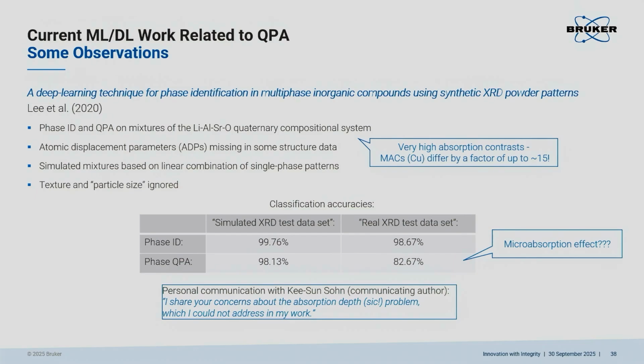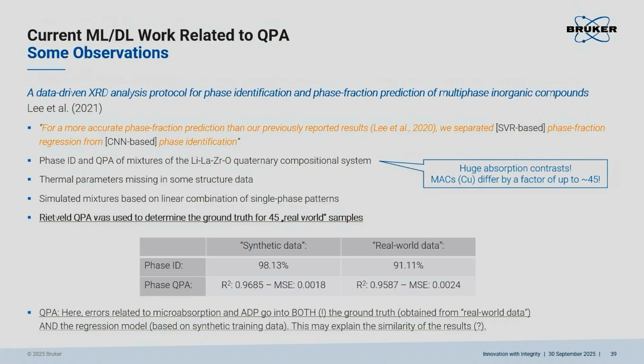So the same authors found the solution to the problem. They used data again, and they evaluated them with Rietveld. The idea is, if we have problems with the classification in the machine learning model, we need to have some ground truth data from somewhere else. So we refine the data with Rietveld, and we claim that the refined results from Rietveld form the ground truth.